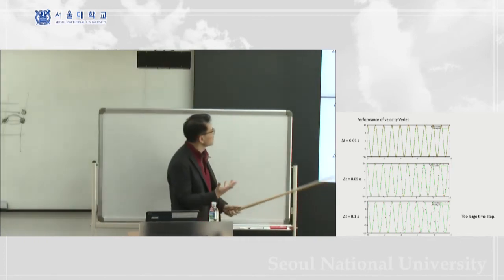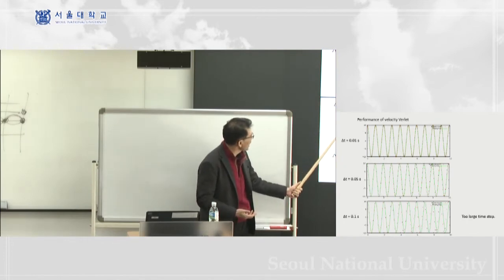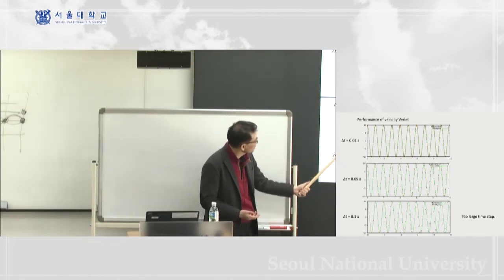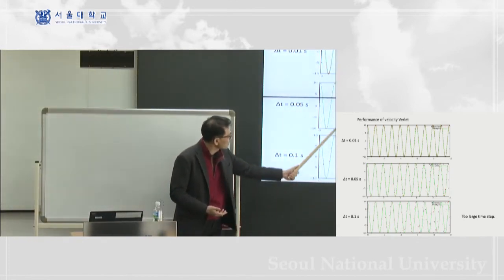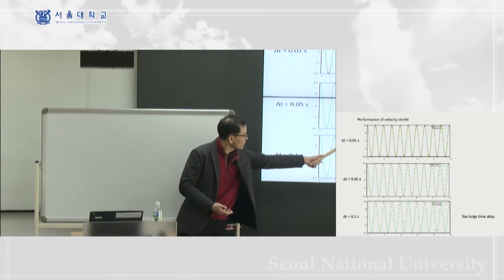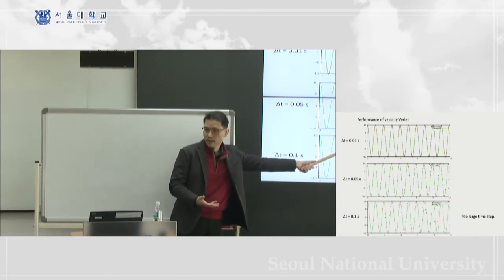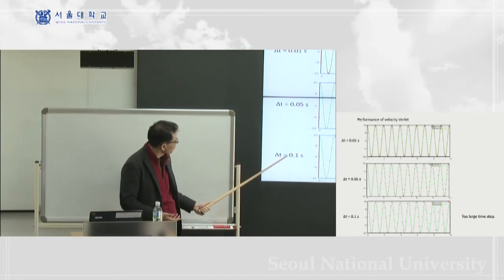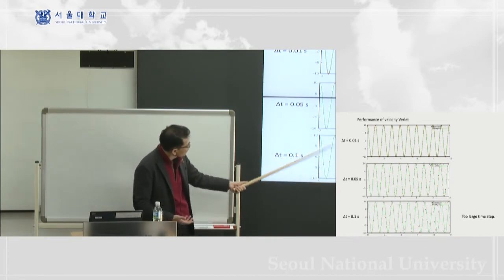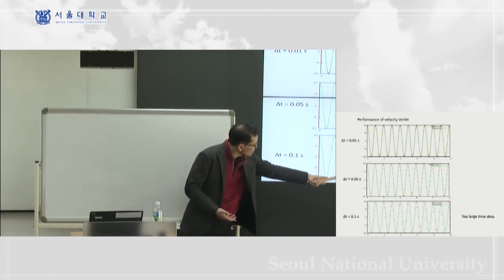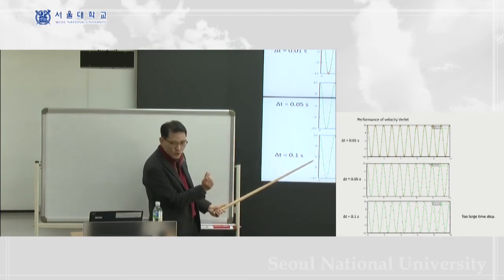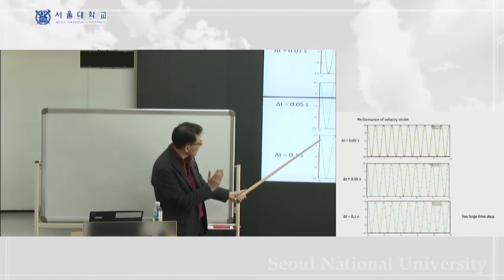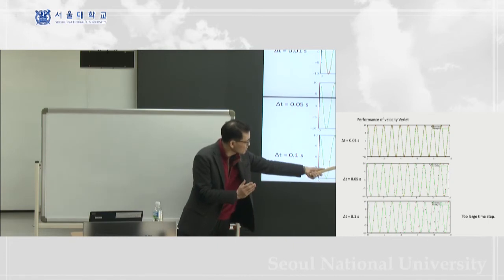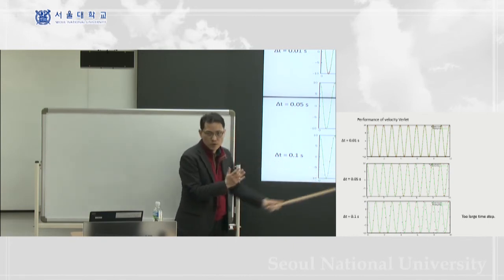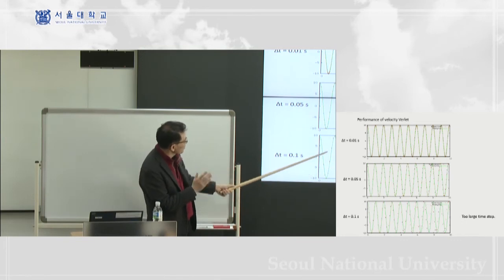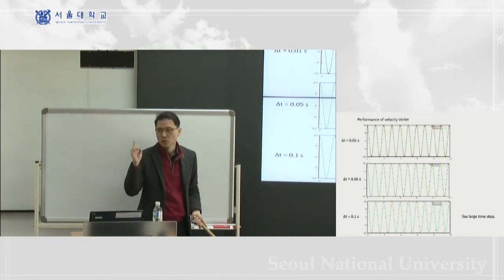And you can even further increase the time step, like 0.05 second, 5 times larger. Then you can see that the red dots still follow the analytic solution pretty well. However, if you increase further, to 0.1 second, then it oscillates reasonably, but because this frequency is slightly different, it lags a little behind the analytic solution. From the simulation, you can see that one oscillation takes about 1 second.